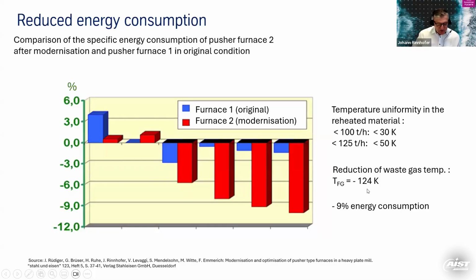Reduction of waste gas temperature means we reduce the energy loss, the sensible energy of the flue gas, so to say, which we lose. So that means the lower the temperature of the flue gas, the better it is. And this is why we have 9% energy consumption in the end. There were a lot of other features, including scaling and other quality issues, which were influenced very beneficially by rebuilding this furnace. But it shows, it's a very typical example of what you can do when you really carefully look at the reheating process.